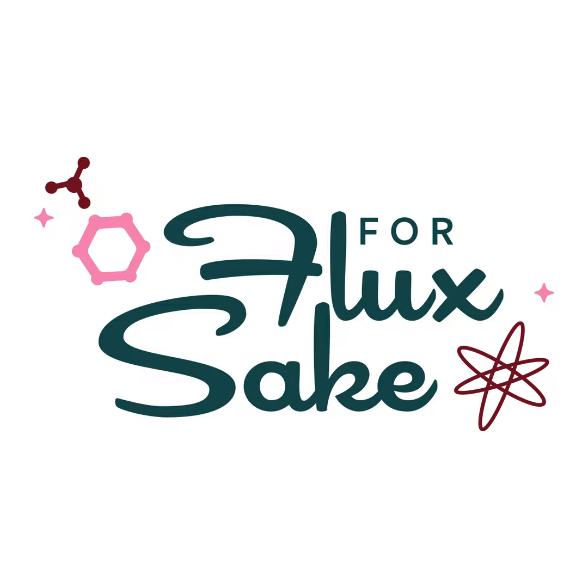But this came up in our studio because we had been using the same glaze recipes for such a long time. When training our glaze mixers, we made the distinction that the bentonite doesn't necessarily need to be in that recipe. It's an additive. And the problem was that no one was treating it like an additive. They were treating it like part of the regular recipe. So we had to extract all the bentonite out of the glazes just to check in and see, well, is it really hard panning? Do we really need this in it? And it was interesting. I think things had changed over time. So some did and some didn't.